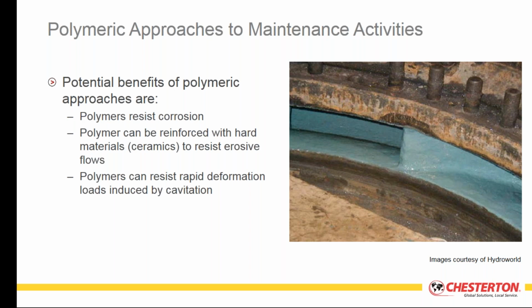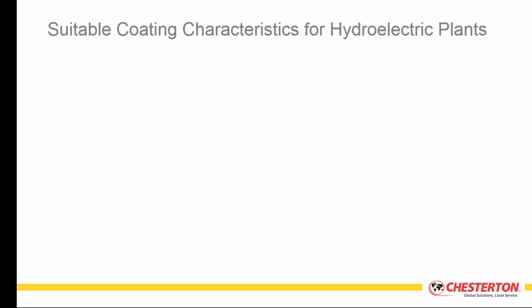These materials could be multi-coat systems. You may be using a paste grade or putty grade material that is used to build up worn regions, in effect using the same technique as the welding approach, where you're building it up and then grinding back down. With coating systems, you can build it up and finish it to the desired thickness. If you do require machining or grinding, it's quite easy, and you're not generating heat stress into that base metal because the polymer itself is not going to react that way. So the polymer-based compound gives you more flexibility.